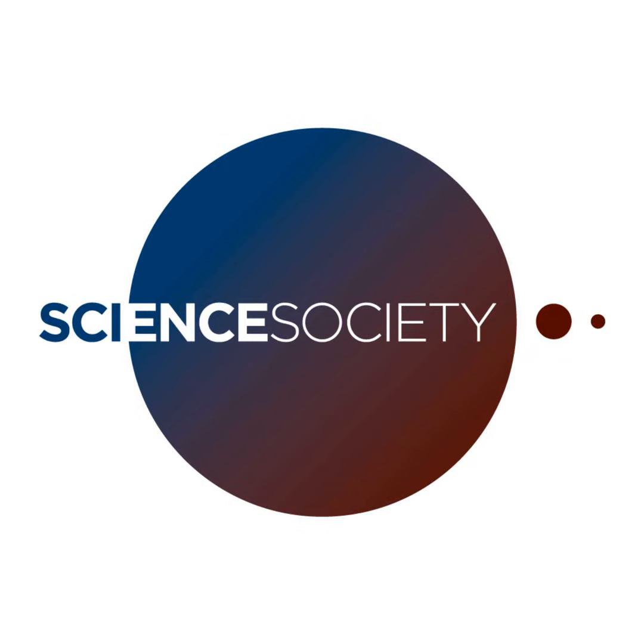So on the aluminum-rich side, there have been a lot of studies, even companies trying to do hydrogen evolution at that kind of ratio. And it wasn't until Isai went to this gallium-rich side, where it remains a liquid alloy just above room temperature, and they varied up to 3 to 1.